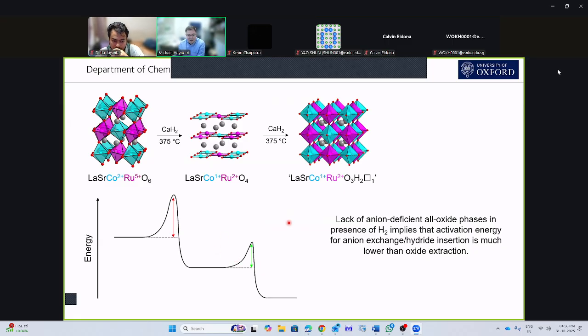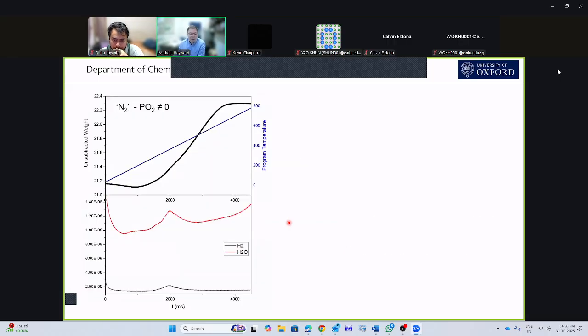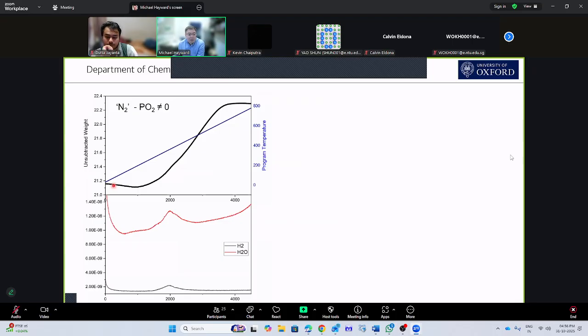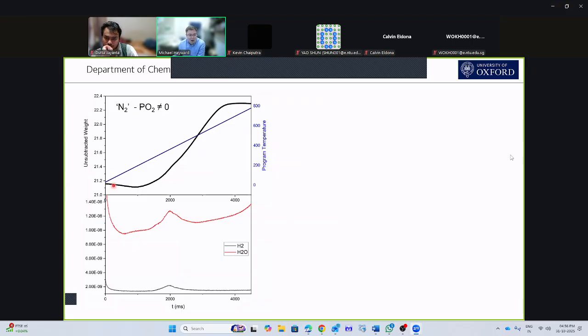And as I was saying before, one bonus we can see is from a TGA measurement. So we often do a TGA measurement. So we heat a sample in a TGA, which is just a balance in a furnace. And if we heat these oxyhydrides under nitrogen gas here, which isn't pure nitrogen, we've got a tiny little bit of oxygen, what we see is they gain mass as they reoxidize. But we can then take the exhaust gas stream and put this through a mass spec. And what we're expecting to see is water from the hydride reaction with oxygen to make water. But we also see hydrogen gas made.